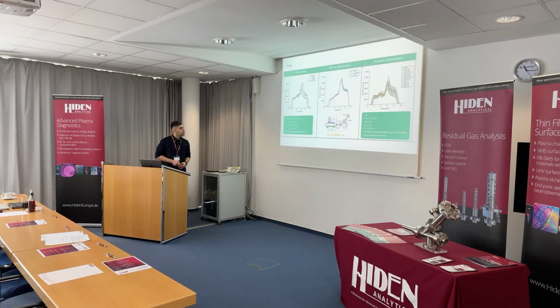So in case of summing both IDF and pulsing modes, this is the shape of the power. And here I speak about measurement errors. The starting time of the IDF measurement after 4 minutes, after 10 minutes, and 15 minutes gave me different IDFs. So I always start the measurement at the same time.